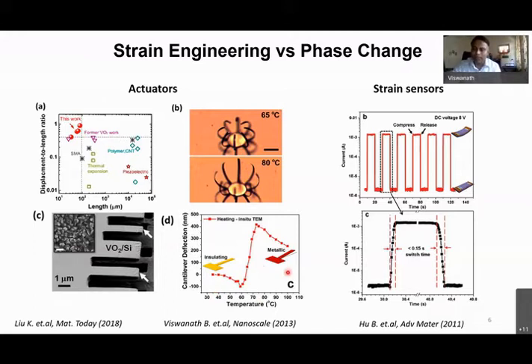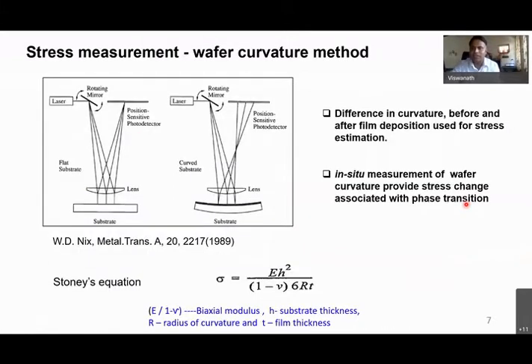On the other hand, the phase transformation can also be induced by stress or strain, which means it can also be used like a strain sensor. Since there are associated electrical properties, for example, the current can be reversibly changed when you are applying compression or tension, which can make a very sensitive strain sensor.